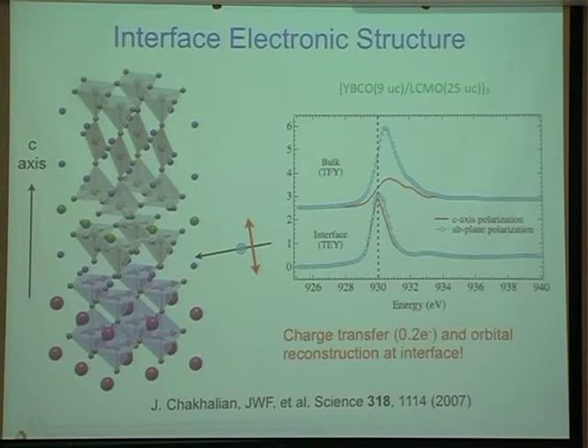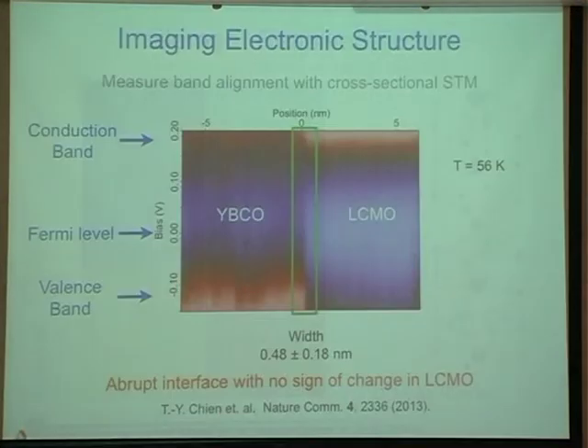And the next copper-oxygen plane looks very much like the bulk. And this is consistent with this idea that the interface is extremely electronically sharp. And so this gives us a very nice system to look at. Unfortunately, this system was not capable of running low temperature STM, so we weren't able to do that experiment to look for the superconducting gap, but I think those are the kinds of things we'd like to do in the future.